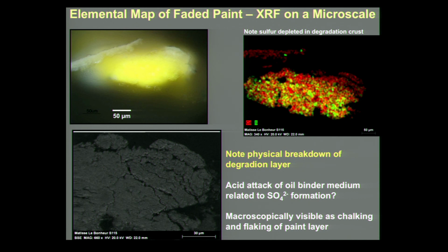Also in the electron microscope, we can see the physical breakdown of the paint layer as well. So you can see all these cracks running through the paint. The paint is actually starting to crumble. So we have a chemical change, the loss of sulfur, and then a physical change as well. And it's thought that this physical change, this crumbling, is a result of acid attack on the oil binding medium that's related to the formation of sulfates when the cadmium sulfide converts to cadmium sulfate. And macroscopically, unfortunately, this is visible in the painting. The paint layer becomes very dry and chalky, and then ultimately it starts to flake off when this happens.